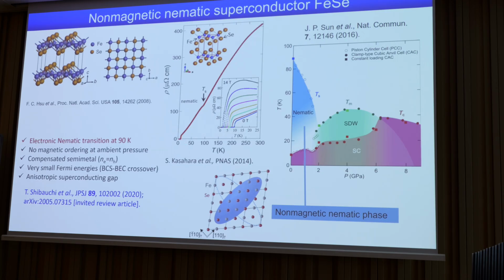So we can actually suppress this electronic nematic transition by applying pressure. But before reaching the so-called nematic quantum critical point, we actually induce magnetic order in this case. And after that happens, the TC rises up to 40 Kelvin. So this is very interesting.